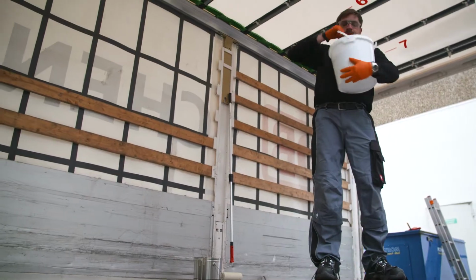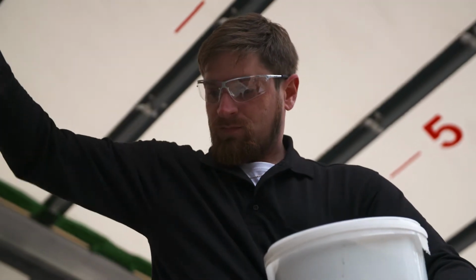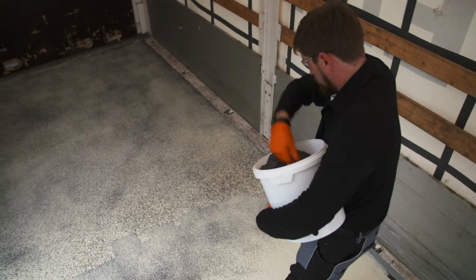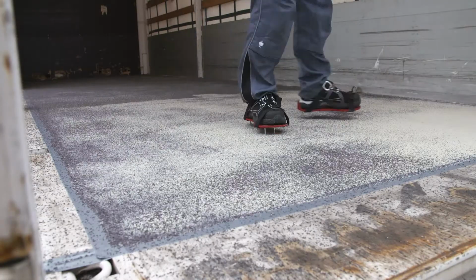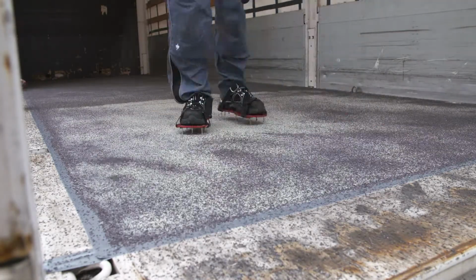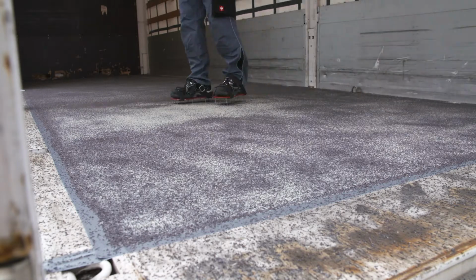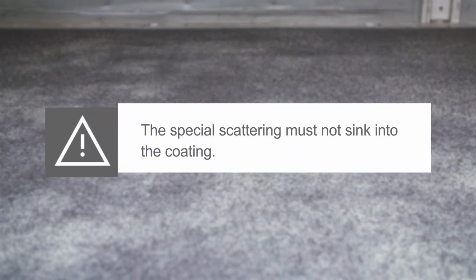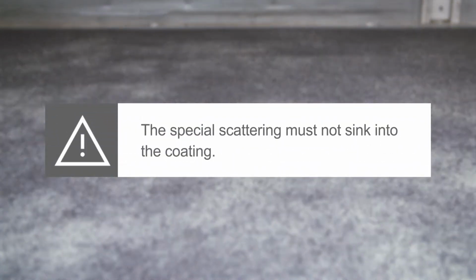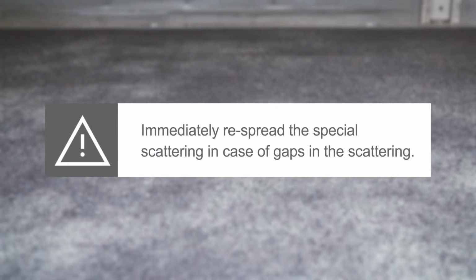After 2 to 3 square meters, the special anti-slip scattering must be spread immediately into the still wet coating. Apply until the scattering is evenly spread across the entire surface grain on grain. Use one 25 kilogram bag of special scattering per measured 9 square meters. The special scattering must be visible and never sink into the coating. If there are gaps in the special scattering, it must be respread immediately.